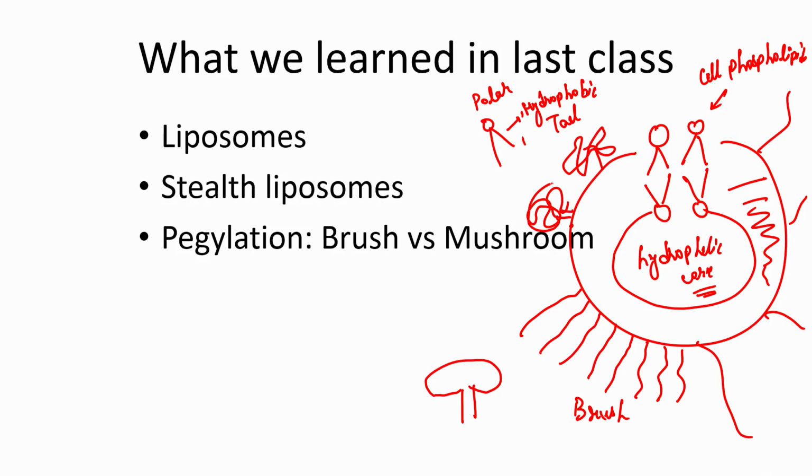So this is essentially that structure here, that these mushroom-like structures have formed of these PEG brushes, and their surface coverage is not as high. So what can happen is potentially a protein can come in and is able to attack the surface of the liposome. So these conformations are not desirable if you are talking about repelling of any sort of foreign object from coming in contact with this liposome. So they do not work as well as, let us say, a brush conformation. So for most applications you would want a brush conformation to be present rather than a mushroom conformation.